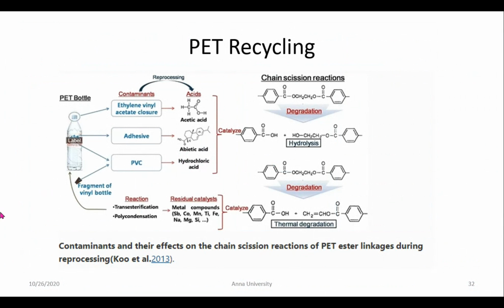So there is every possibility for the entry of PVC bottles into the waste stream of PET bottles, because separation of PET and PVC is not that easy because of their very close densities. Okay, so there is every possibility for the PVC bottle to enter into the PET bottle stream. So the lid, if we do not completely remove it, a small amount of lid that enters the PET bottle stream will evolve acetic acid, because it's a copolymer of ethylene vinyl acetate. So it is found to liberate acetic acid, and the adhesive also gives out abietic acid. PVC, which contains chlorine, is found to undergo degradation at the processing temperature, or say at the recycling temperature of PET bottle, producing HCl gas.